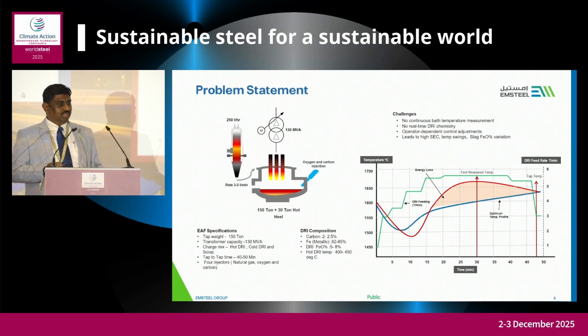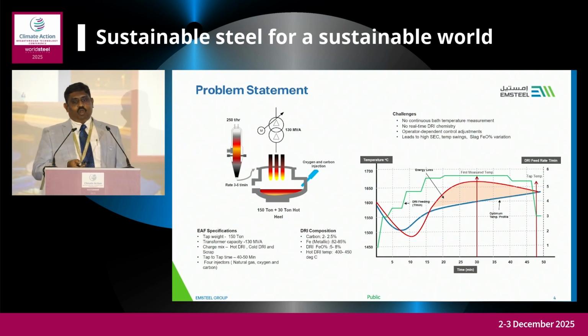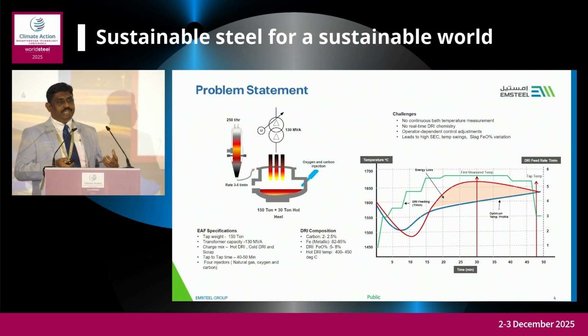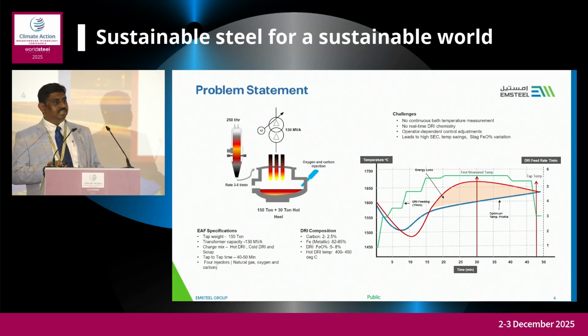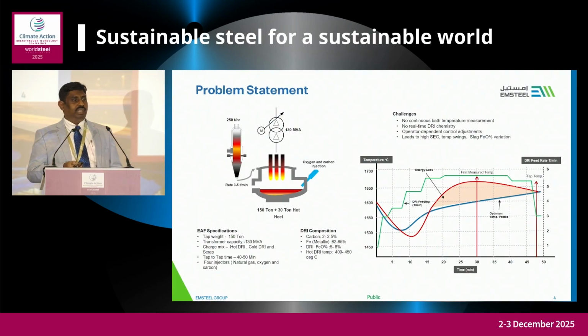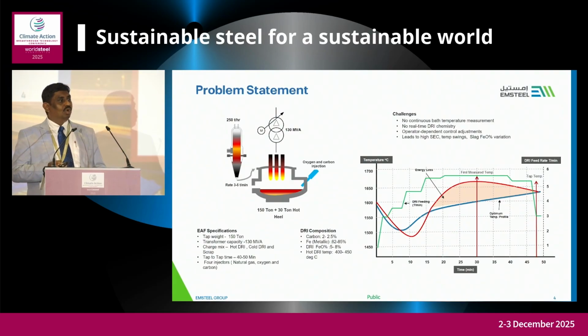So if you see the plot here, the operator, when continuously feeding the DRI, faces challenges due to non-availability of online temperature measurement. Whenever you take the temperature, it's around 30 minutes, and sometimes the temperature is higher, and that will be a loss of energy. If the temperature is already highest, then he tries to reduce the DRI feed rate to control the temperature, which impacts productivity. So there is energy loss and productivity loss.